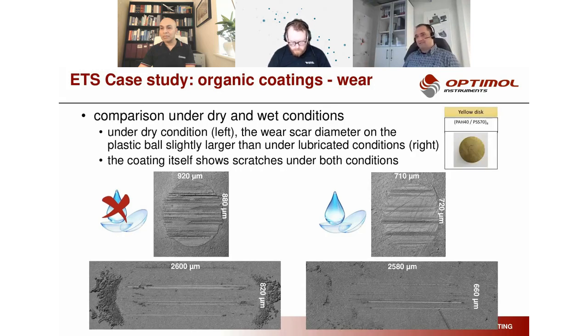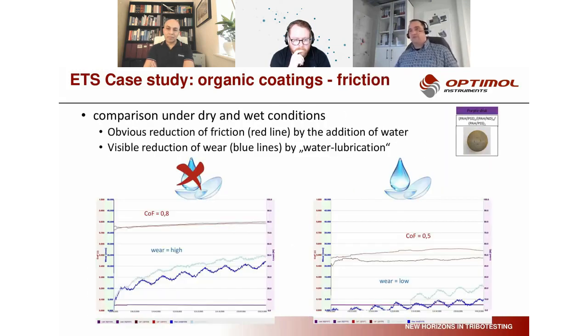While this yellow disc, for example, produced in both cases, wet and dry, damages on the surfaces, the wear tracks look relatively destroyed and damaged, and this already disqualifies those coatings for the target application. If you compare the friction and the wear